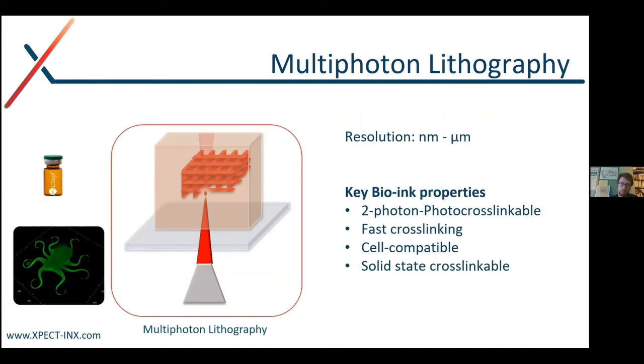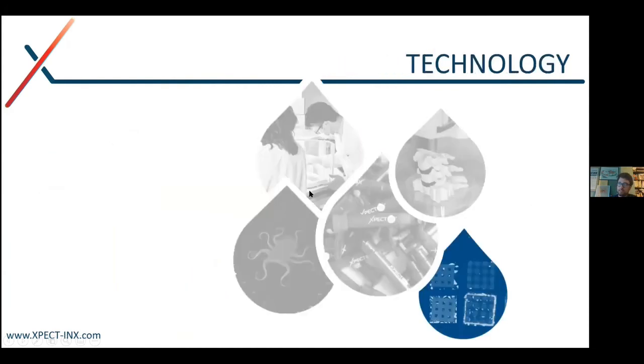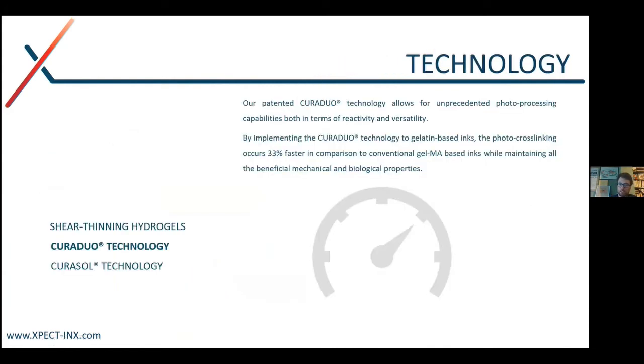So first of all, most importantly, they need to be 2-photon active. You want them preferably to be very fast cross-linkable, because of course the higher the resolution, the more lines you have to write to generate a construct of the same size. You want it to be cell compatible, and there can be a benefit if it's solid-state cross-linkable, because in this technology, you can freely scan your voxels in 3 dimensions, meaning that if you do this in a solid, your uncross-linked material can act as a support for your newly formed cured material. So fortunately, we can also rely on some of our technology there.